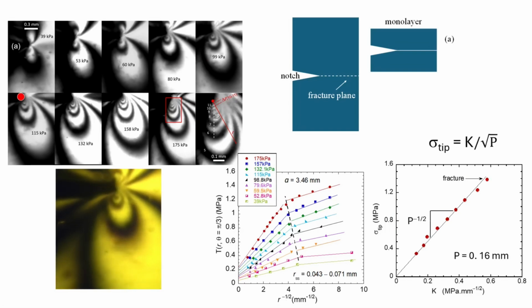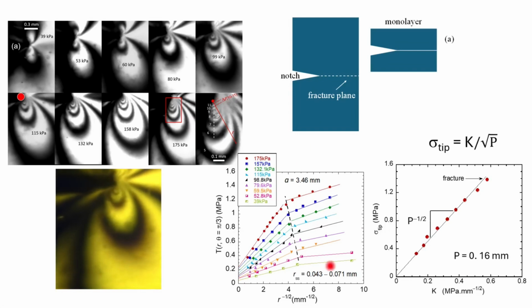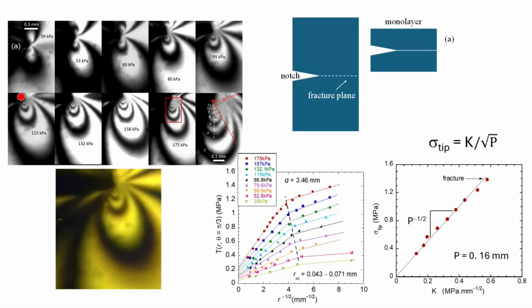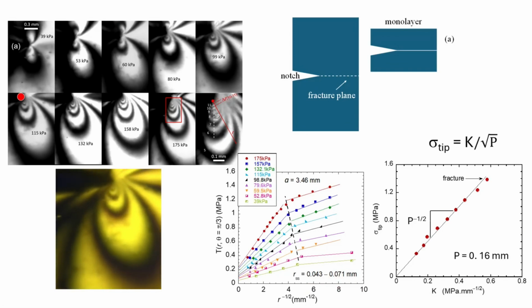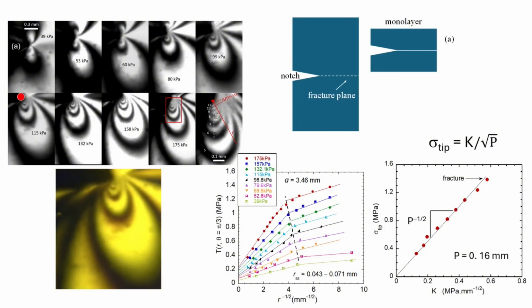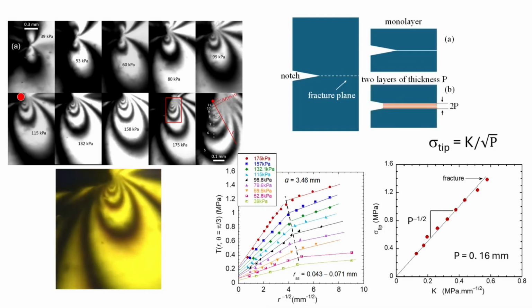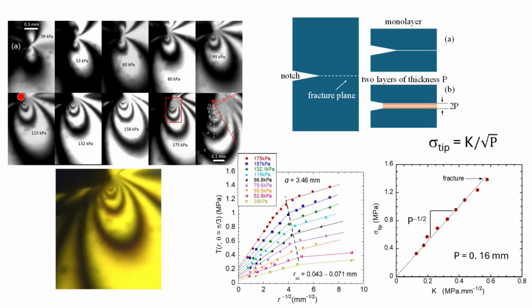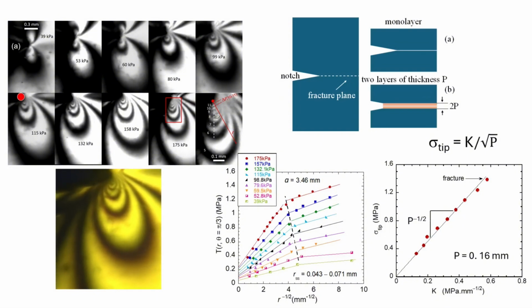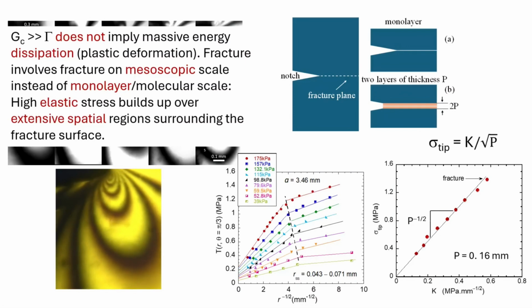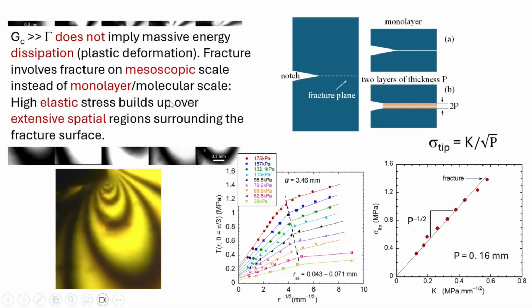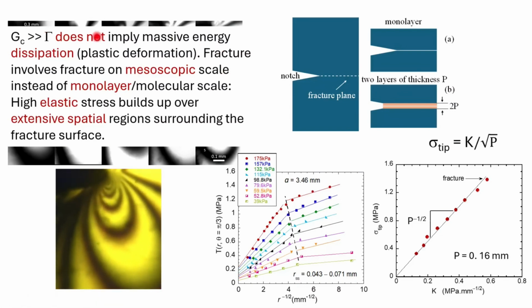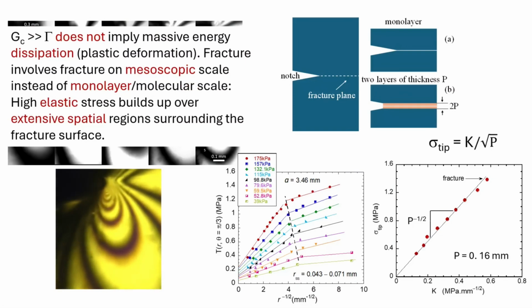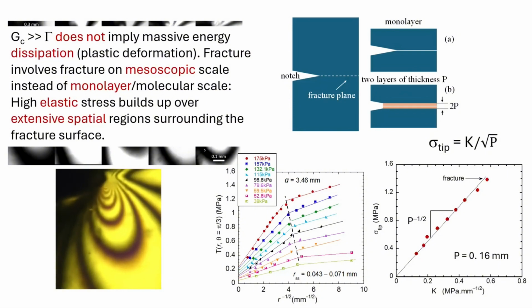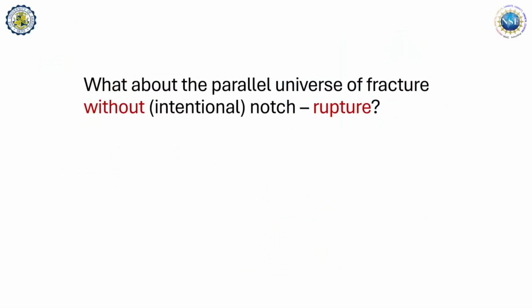So what did we learn? 2 things. This stress saturation happens on 40 to 70 micron scale. We learned for sure, consistent with all the observations that Constantino and Gaebel have, that the fracture is not happening just involving one monolayer. It's a huge layer. That is where the characteristic length scale came out. Therefore, the energy release is a huge, huge number because of this. I have said what I need to say. Really, the high amount of toughness has nothing to do with a massive dissipation, but has to do with the fact it doesn't involve a monolayer. So, how do I conclude that way? Because we're looking from a stress viewpoint. Well, so far so good.